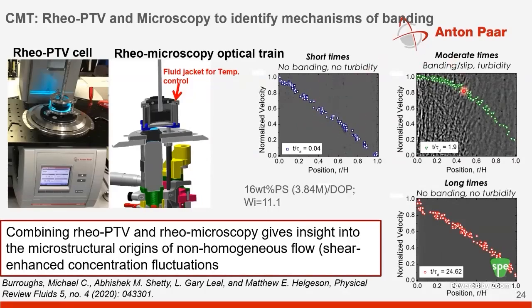But at moderate times, you see non-homogeneous structures which you can actually observe through microscopy, and at the same time there is shear banding happening, with two different velocity profiles forming in the sample. Then if you keep shearing for long times, these bands go away, which is why they're called transient bands. This is the power of combining rheology with other techniques like particle velocimetry and microscopy, giving insight into the microstructural origins of when flows become non-homogeneous.